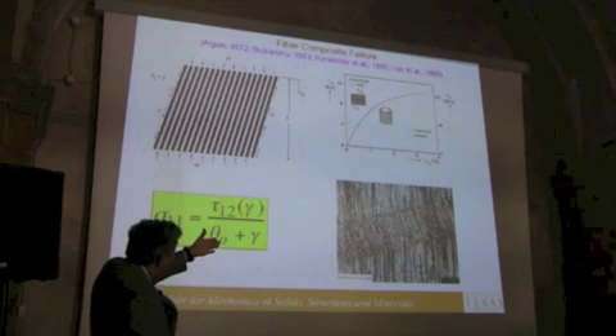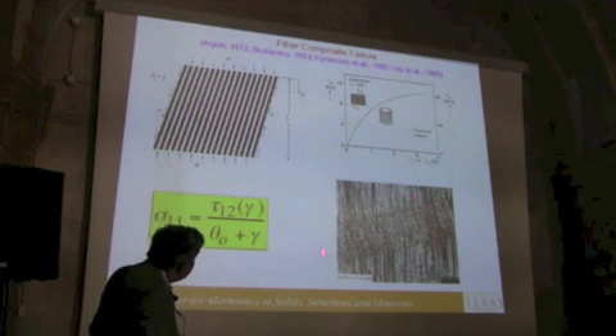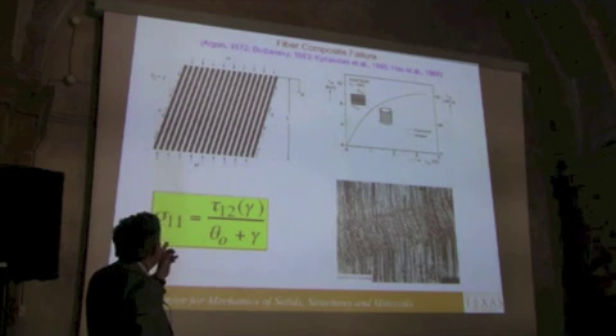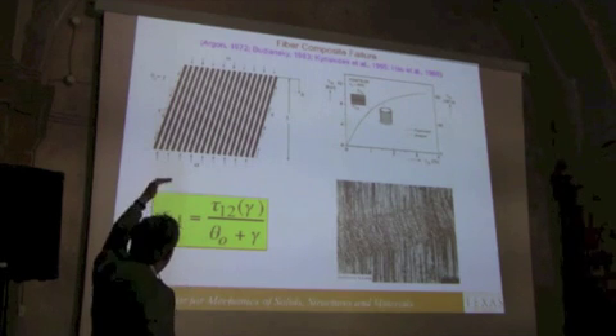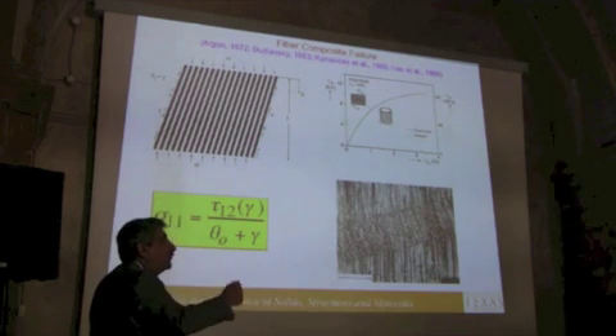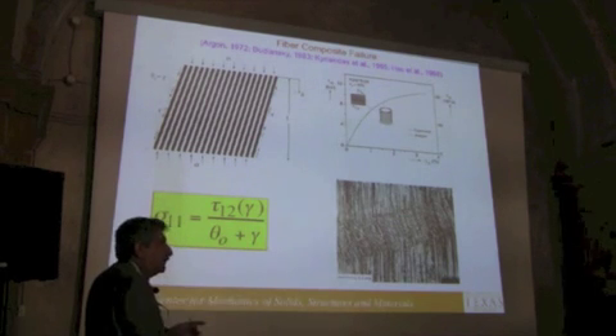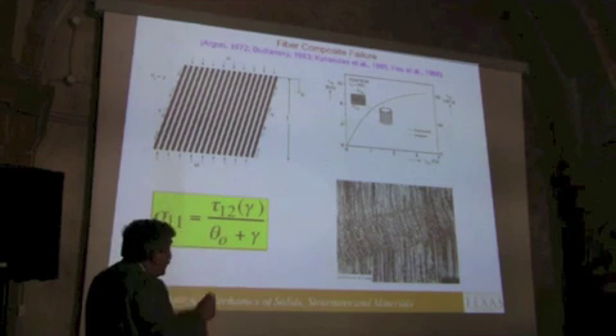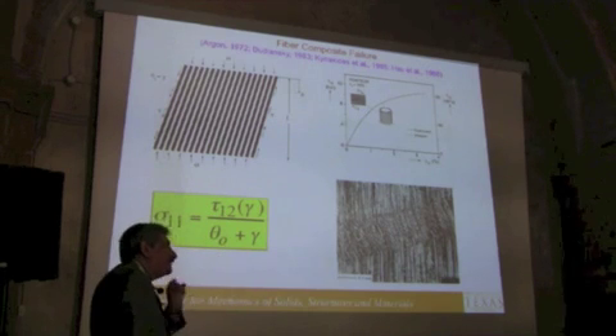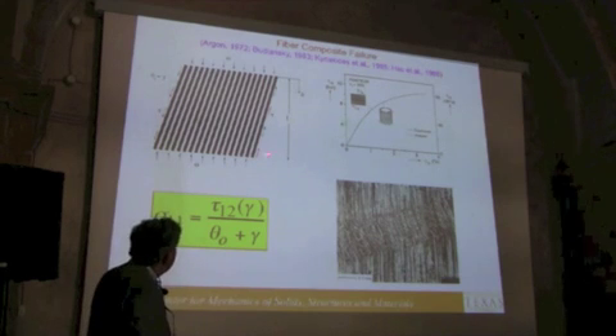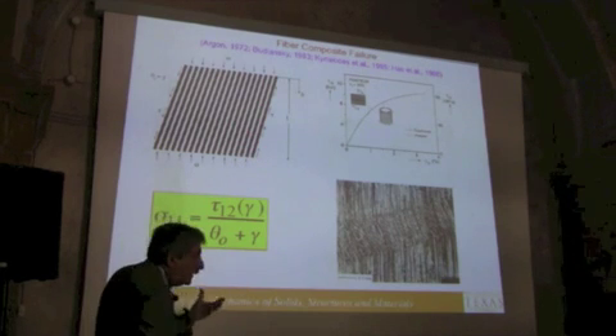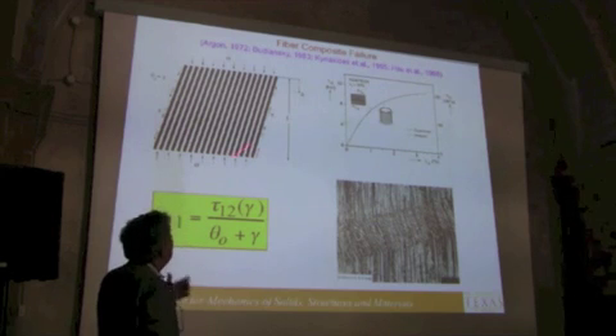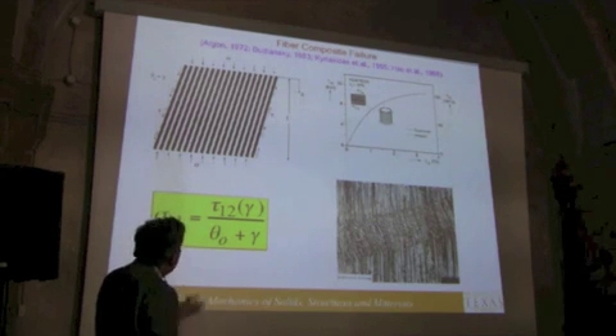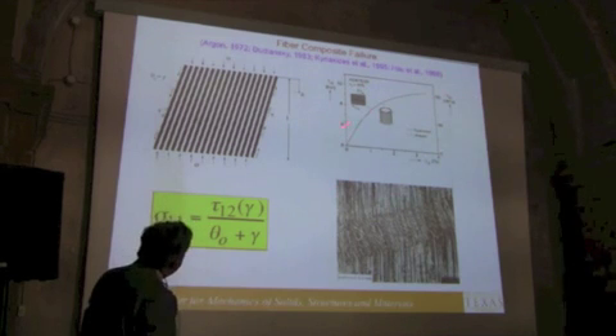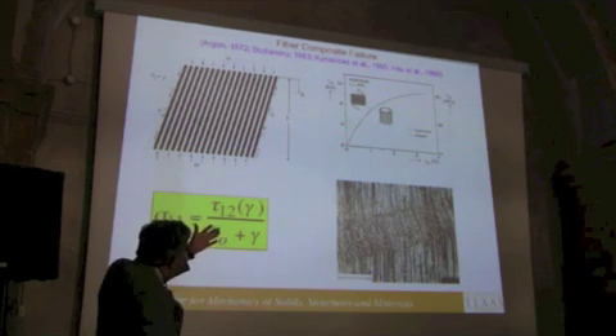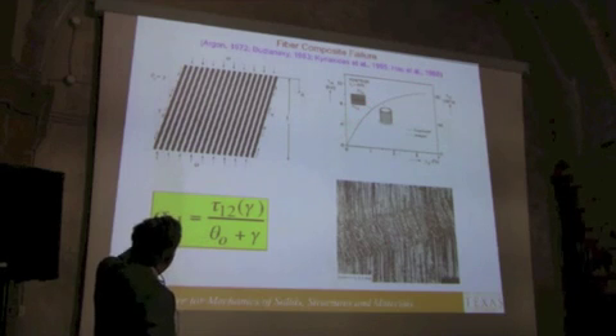In compression it is due to kinking of the fibers, and kinking is this thing here. What is the mechanism? The mechanism is the following. You compress this, and it tends to develop microbuckling. This is a problem that goes back to the 60s, microbuckling. But the microbuckling is not elastic. The reason it's not elastic is because the matrix is non-linear, and let us say we can call it elastoplastic. The shear response of the material is like this. This is the measured shear response of the material.